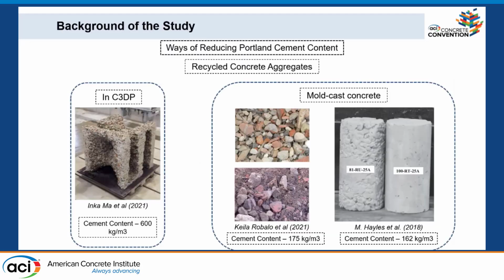So, one promising strategy to reduce cement reliance is incorporating recycled concrete aggregates. Traditional concrete demolition generates vast amounts of waste. By crushing the old concrete, we can reuse it as aggregates, lowering the need for newly mined minerals. As you can see, researchers have successfully used RCA in both 3D printing, using 600 kg per cubic meter of cement, and traditional casting methods, like 162 kg per cubic meter of cement. This demonstrates the feasibility of reducing cement while maintaining structural integrity.